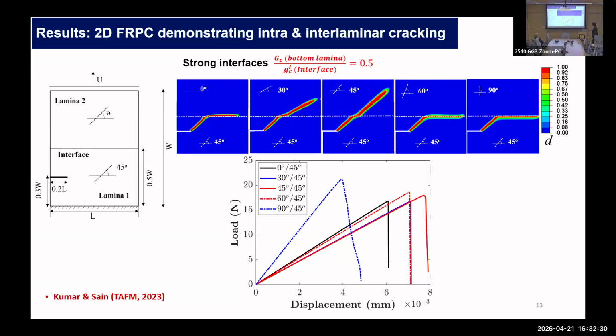Okay. So what we see here is pretty interesting: as the top fiber orientation changes from 0 to 90 degree, the propagating crack path changes. For all of these cases, the crack starts at the notch tip, follows 45 degrees, the bottom fiber orientation, then reaches the interface, stays there for a little bit, but then goes up and follows the top fiber orientation up until the 45 degree cases.